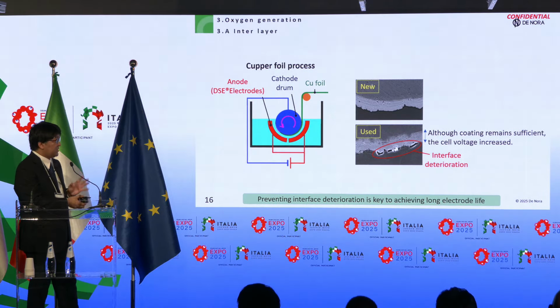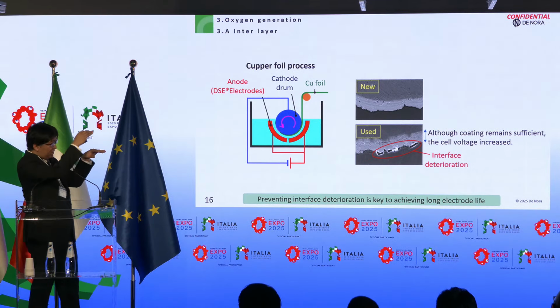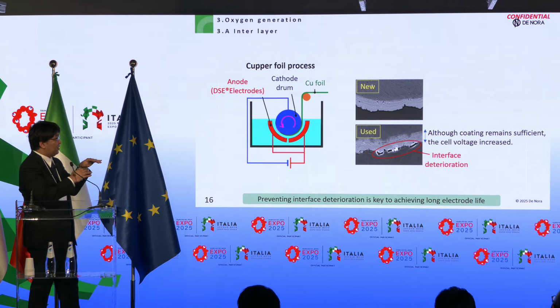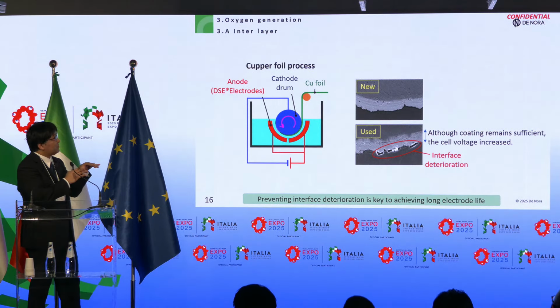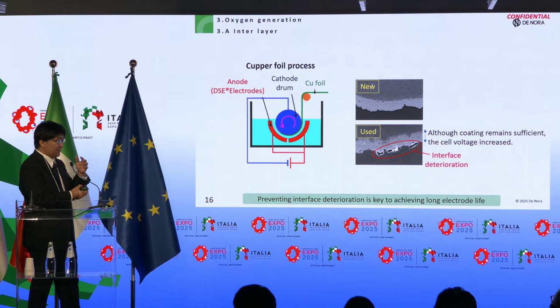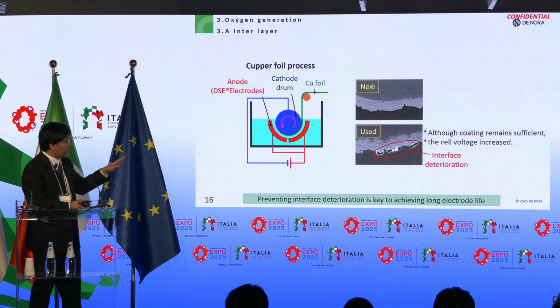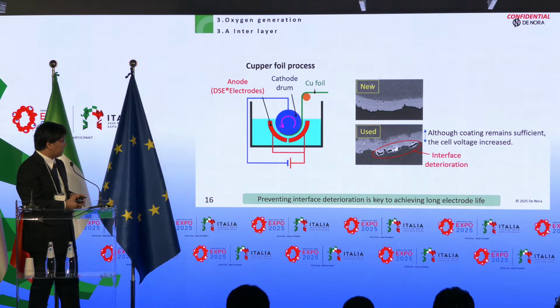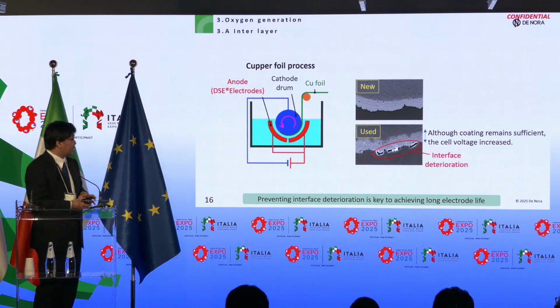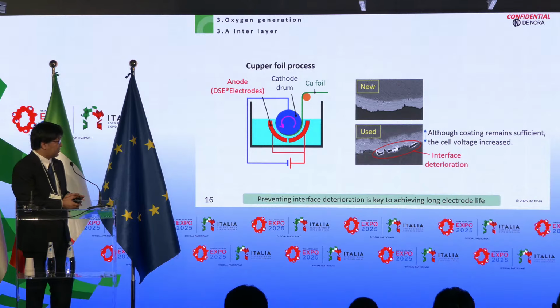In case of the chlorine generation anode, the catalyst is consumed from the top and gradually decreased. So it can expect the life easily, but in case of oxygen generation, interface deterioration can also occur. So preventing interface deterioration is key to achieving long electrode life.